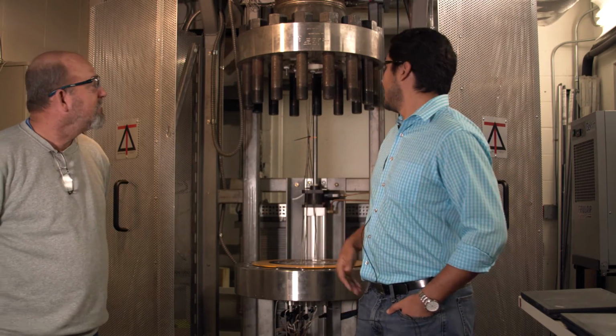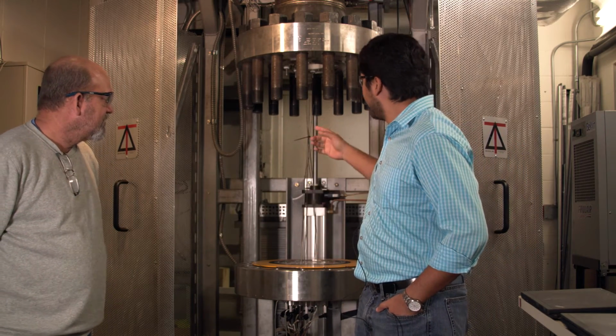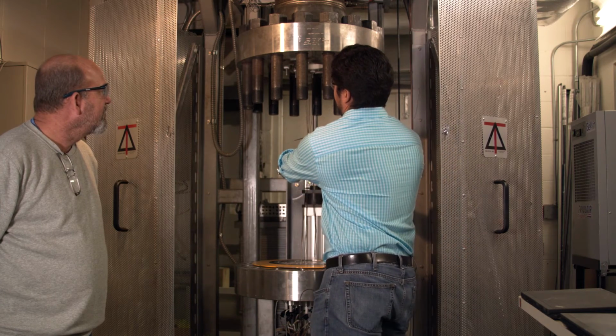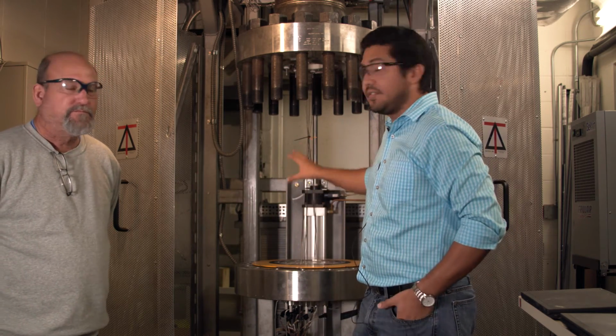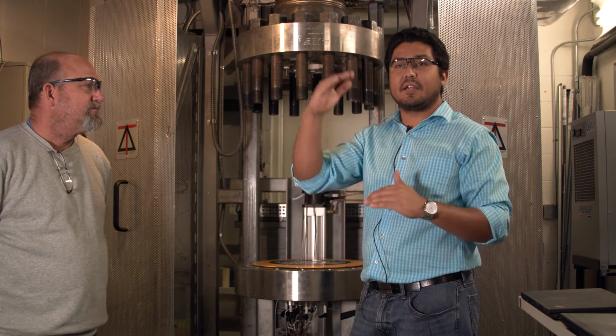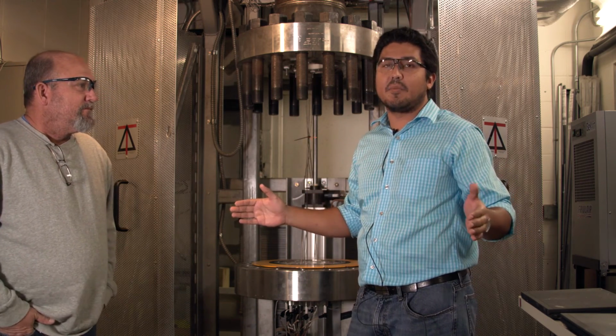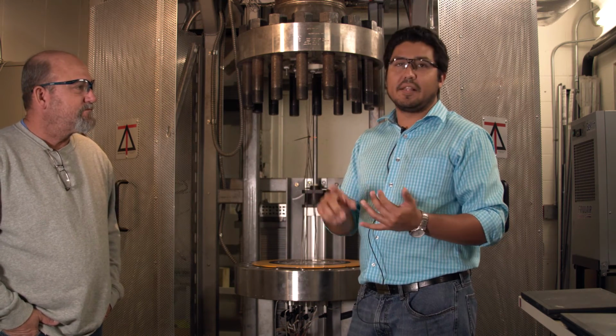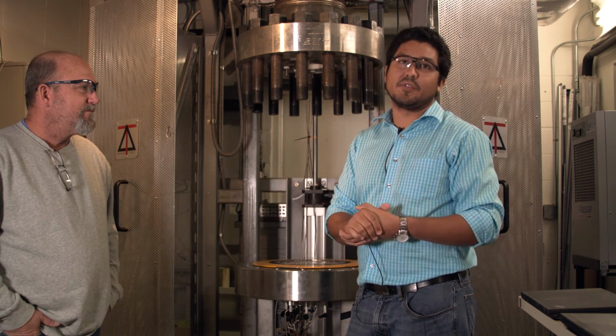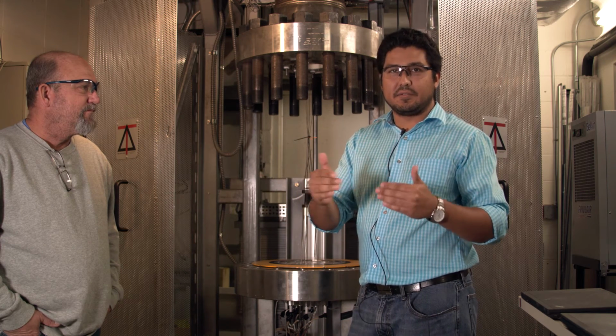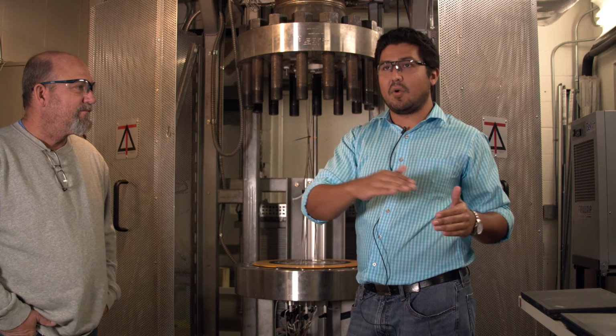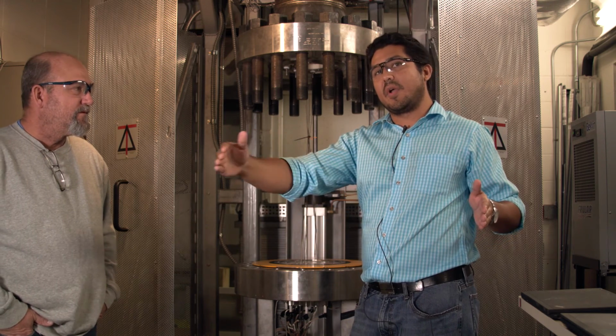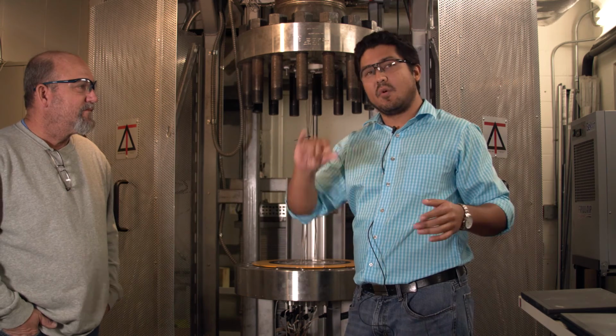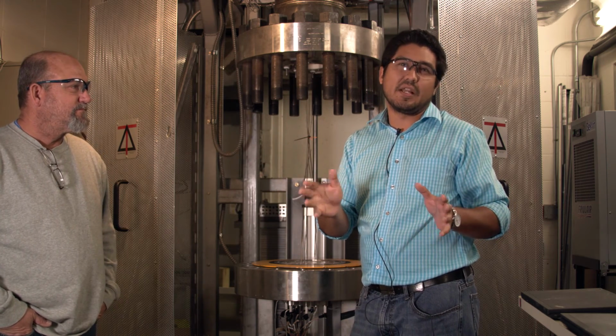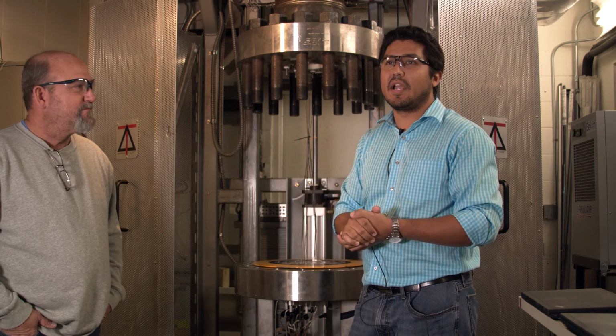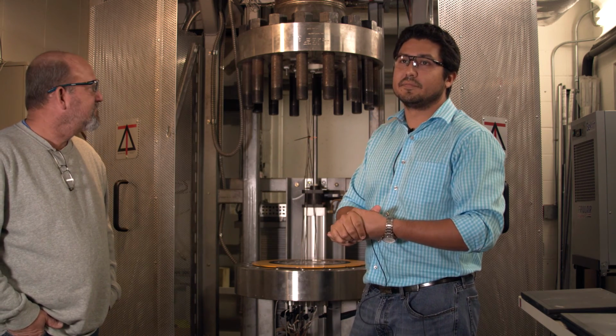So now that we have the furnace open, this is essentially what we work with. The inner space is about yay big, 5-inch in diameter, and we have a multitude of thermocouples inside so that we can actually take temperature traces throughout the entire process. And with that, we can balance and tune the furnace, and we can heat treat these coils to within about a degree differential across an entire coil through the whole heat treatment, from room temperature all the way up to about 900 degrees centigrade and back. We'll have a differential of no more than about 1.5 degrees or 2. So again, pretty high precision research development furnace.